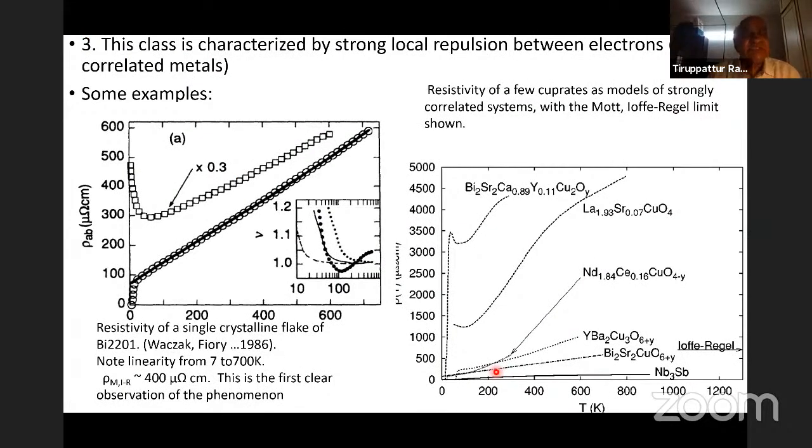This quantum upper limit is a guess. It is a guess based on the following idea. Suppose the wavelength of the electron, which is the de Broglie wavelength of the electron at the Fermi energy, that is approximately of the same size as the distance an electron has to travel before it scatters. That should define some characteristic conductivity or resistivity below which the mean free path for collisions cannot go. In this particular class of clean systems, the resistivity is not only large but it does not seem to recognize that there is an upper quantum limit to resistivity. It seems to increase linearly well beyond that limit without saturating. This class of materials in which it occurs, they all seem to be characterized by strong local repulsion between electrons. That is, these are what is called strongly correlated metals.